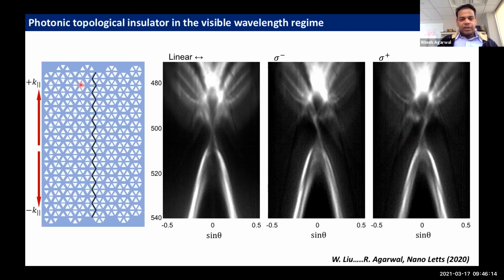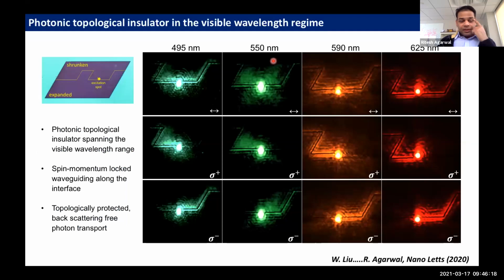So we have propagation in one direction or the other direction, depending on the polarization of light. This is a more striking example of this. We shine different colored lights. These are different photonic structures because one has to be in resonance. But this can only happen in the band gap regime, where we create this photonic gap. So with linearly polarized light, we have transport in both directions, and then right or left circularly polarized light basically transports the photons in different directions.